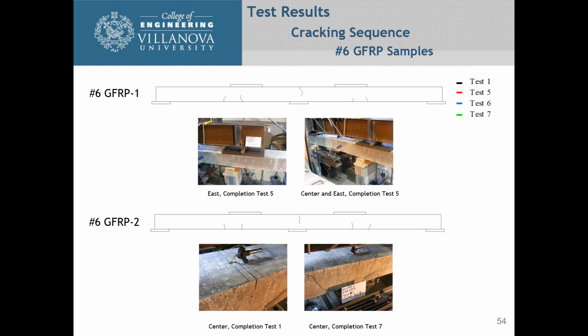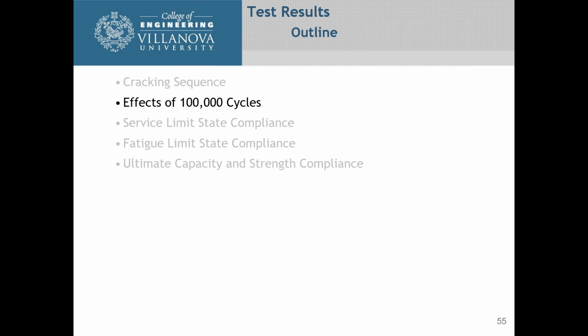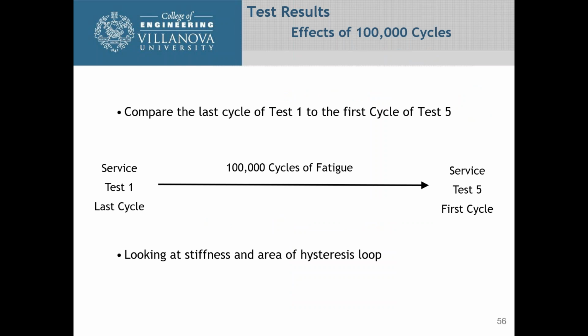For the number 6 bars, we saw a lot more cracking under the first phase, under test 1. Then when we went to test 5, you saw an extension of the cracks, but no additional cracks were forming. Under test 6, you can see how we got more cracks in the negative region and a lot more flexural cracks. Again, you can see flexural cracks here, diagonal cracks here. In test 7, just saw an extension of all those. So let's take a look to see what happens due to the 100,000 cycles.